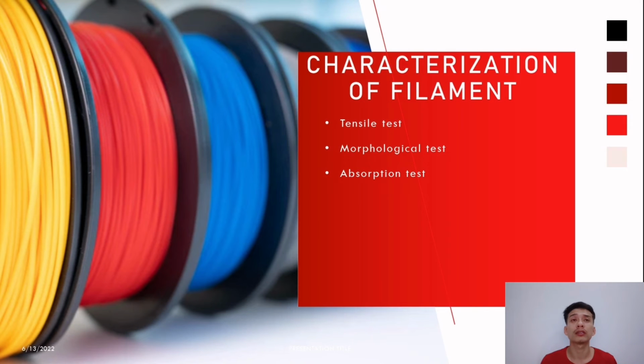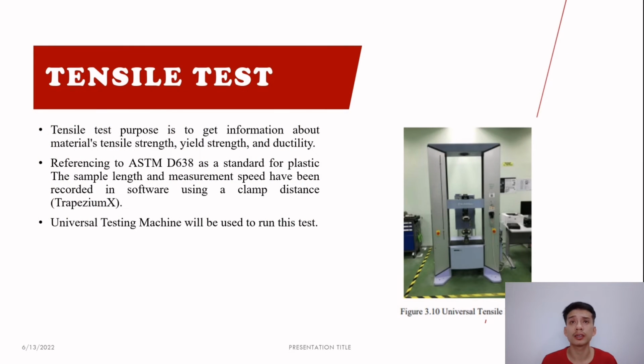Lastly, the characterization of the filament, where we do tensile tests, morphological tests, and absorption tests. For the tensile test, the purpose is to get information about the material's tensile strength, yield strength, and ductility. By referring to ASTM D638 as the standard for plastics, the sample length and measurement speed are recorded in the software using a clamp distance. A universal testing machine will be used to run this test.